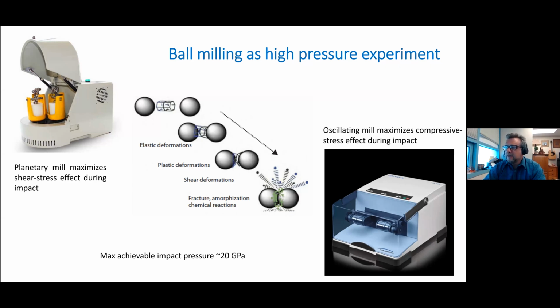If you look at the physics of collision of spheres, and if you put a piece of sample, or pieces of two materials that could react under stress with each other, between two spheres that fly at high speed against each other and collide, you can see that first of all, there's quite significant pressure that you can achieve, depending on the size of the spheres, their speed, and compressibility. There are also a lot of different phenomena that happen during the collision, starting from simple elastic deformation through plastic deformation, shear, fracture, amorphization, and leading to basically inducing polymorphic phase changes as well as chemical reactions.